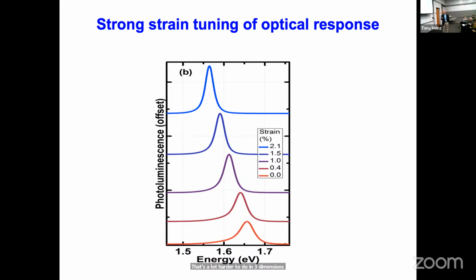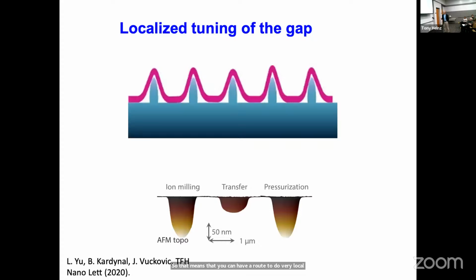So that means that you can have a route to do very local modification of the material and the band structure. And this is a kind of thing a lot of people have been doing. They've milled some kind of pattern in the substrate. This is obviously very exaggerated here, but you have some kind of protrusion, and then you deposit your monolayer on top of it. And that's going to create an inhomogeneous strain field. And in particular, you're going to see a lot of strain up here, which will lower the band gap.